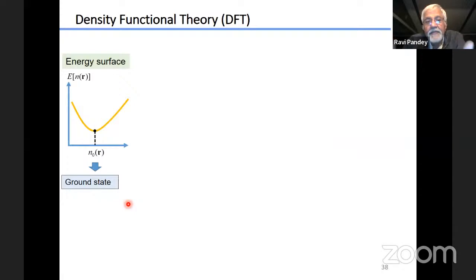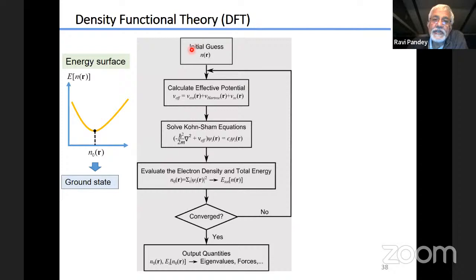Our aim is to find the ground state of the system. So you start with an initial guess of the electron density. From there, you calculate the effective potential. Then you solve the Kohn-Sham equation, and you go back and evaluate the electron density. This is an iterative process. You find how different the calculated electron density is from the initial guess. If this difference is very, very small, then we say our calculation is converged. From there, we have the ground state electron density and the ground state energy. Once you have these, you can calculate any property of the system. That's the key thing here, how to get this ground state, and it all depends on your educated guess.